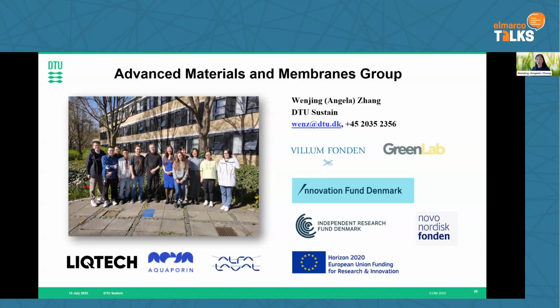Another question from the audience. Have you investigated other photocatalysts, maybe also for hydrogen production? Observed any degradation of the polymer and the interface? Yes, that's a very good question. We are now working on green hydrogen production with our nanofiber electrodes, and we see the performance boosted quite dramatically. For the degradation part, I think it is very tricky. Especially for polymer, if it's an alkaline electrolyzer, then at the very high pH value of the electrolyte, the polymer has a very, very tough time. So that's why we are now looking at replacement of those polymer materials. That's the work we are doing at DTU at the moment.